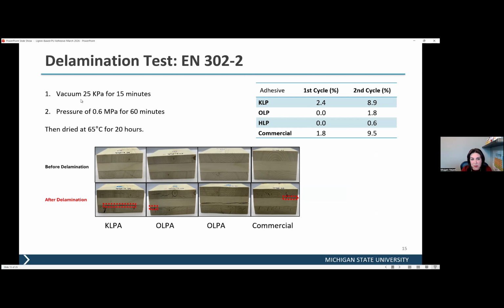The cycle starts with vacuum pressure at 25 kilopascals for 15 minutes. And then after that, applying pressure of 0.6 megapascal for 1 hour. This is the first cycle. And then we're going to do another second cycle, again repeating this.